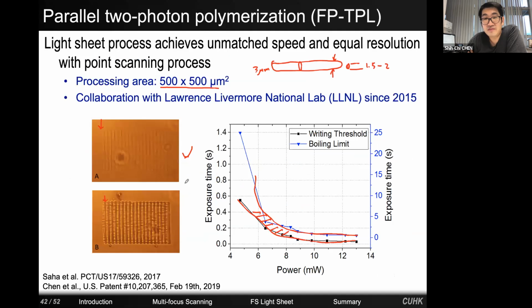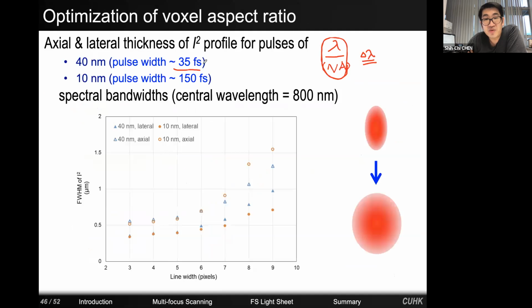So we get wider spectrum here, but we purposely cut off some colors. So point spread function worsened. But we're very lucky to find that the lateral resolution is worsened at a higher speed than axial resolution. So by appropriately adjusting the color that we clip off, the spot size becomes round, and of course it becomes bigger. But bigger in size doesn't matter as long as we control the laser power threshold. We can write smaller spots.